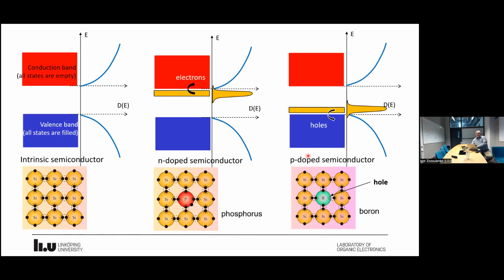Another case is the so-called p-doped semiconductor, p for positive. In this case, let us consider that instead of phosphorus, you have boron, and boron has only 3 valence electrons. This means that there will be one bond not formed, and such a bond not formed would correspond to a hole. It corresponds to a quasi-particle that we call a hole, a positively charged quasi-particle corresponding to the absence of an electron. This absence of the bond can jump around the crystal, so we say that the quasi-particle hole jumps around the crystal,